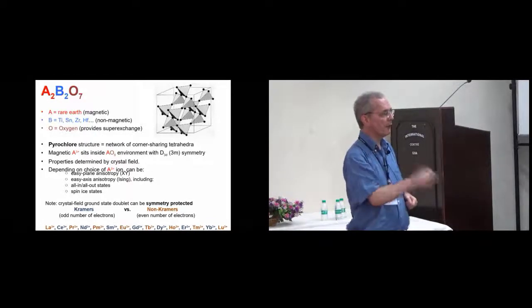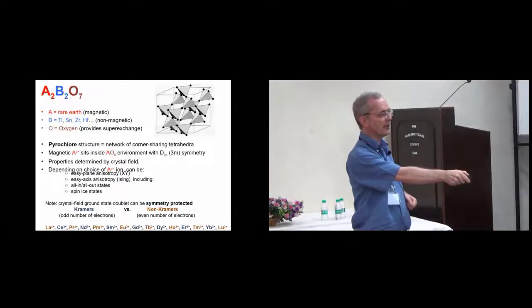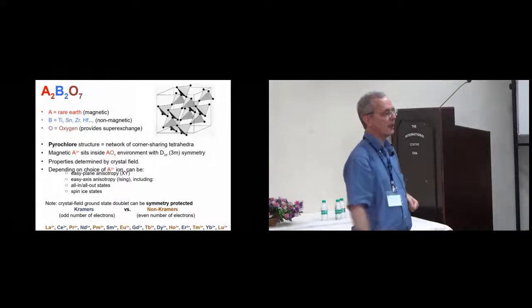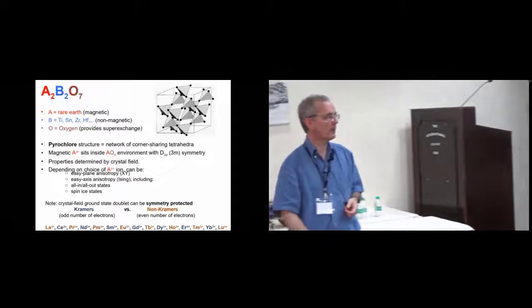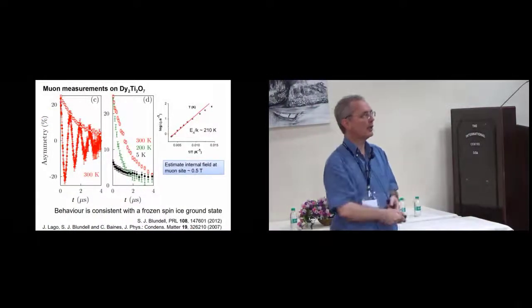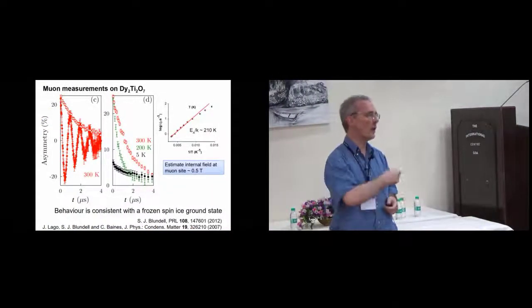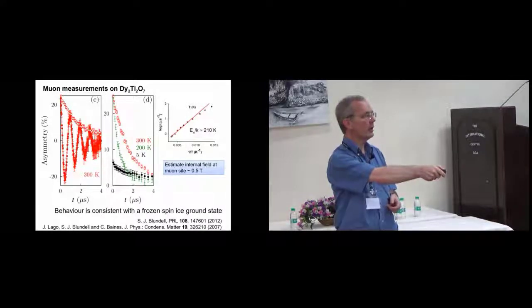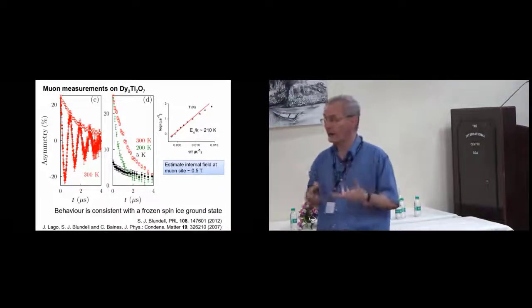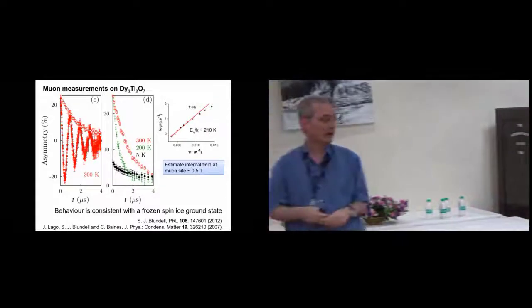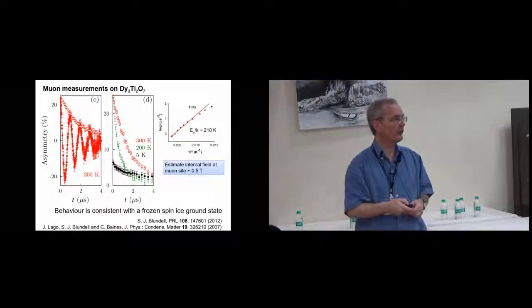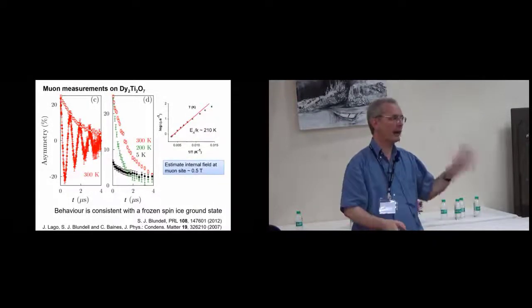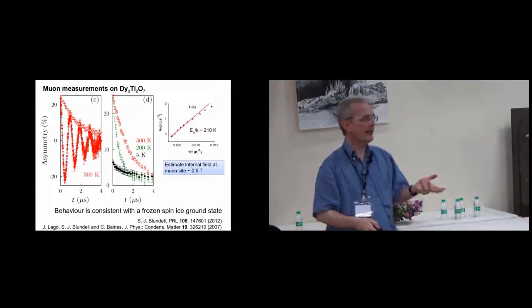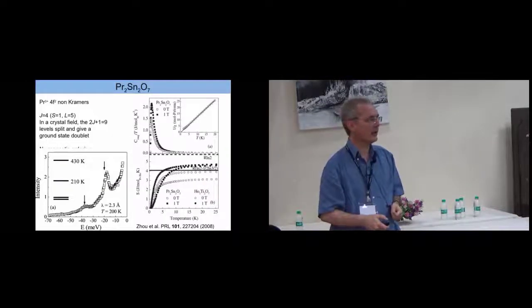Now, the famous material here is dysprosium titanate. This has the dysprosium ion in, and this shows spin ice properties. Here is dysprosium titanate with some muon measurements. I won't go into the details, but essentially the behavior is consistent with a frozen spin ice ground state. This is something we looked at a number of years ago, and there was a big controversy, but I won't go into that. So we know that the internal field is around half a Tesla, and there is a frozen spin ice ground state at low temperature.